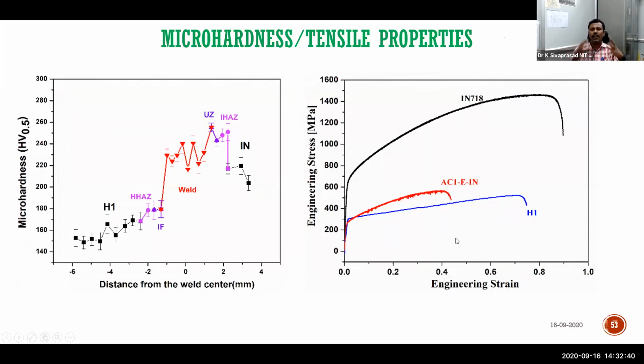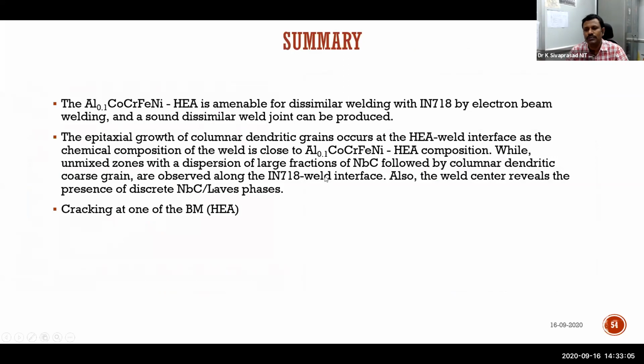Because wherever hard and strong phase combinations are there, if the interface is weaker, suddenly a void will form. The moment a void forms, it has touched UTS. Afterwards it is a dip only. If you postpone that, probably the curve will go up like this. So if you are able to postpone your necking conditions or void formation in the microstructure, you can get high strength and ductility combinations. That's what is proved.